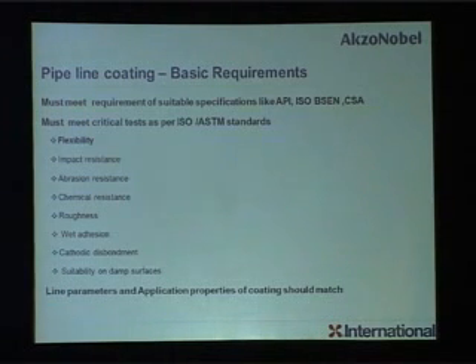Roughness, definitely for a gas pipeline mainly. Wet adhesion, very, very important. Like, there are a lot of chemicals. If you are transporting through pipes at higher temperature or ambient temperature, your dry adhesion and wet adhesion are very, very important for coating. You check adhesion in dry condition without putting in chemicals, and you check adhesion after exposing to chemicals. There are chances of adhesion loss if your coating chemistry is not proper. So this is very important to test. Definitely the cathodic disbondment test, we all know, very important.